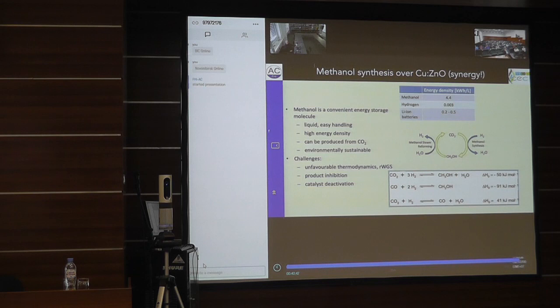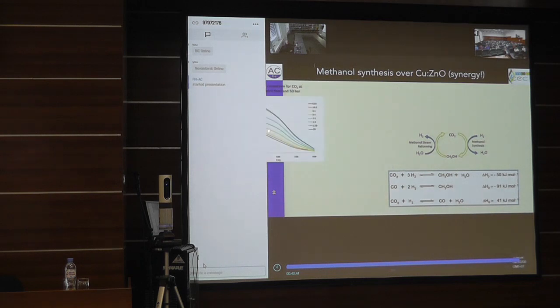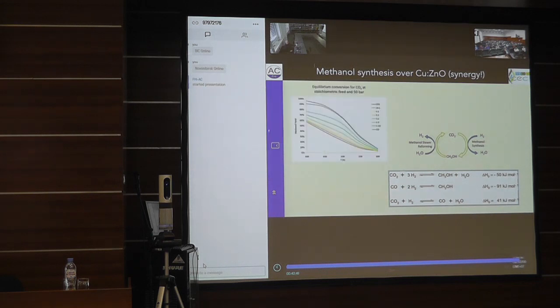Okay, the equilibrium limitation is severe. As you can see here, the red line is the CO2 equilibrium at 50 bar pressure, and the catalysts that we have operate in a temperature window between 470 and 550 Kelvin. So we get an equilibrium conversion of roughly 20%. That's all you can have, equilibrium. And this means that this idea of a methanol economy that you might have heard from Mr. Olah has of course also this limit.